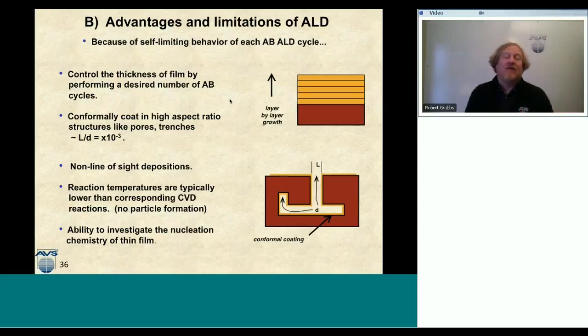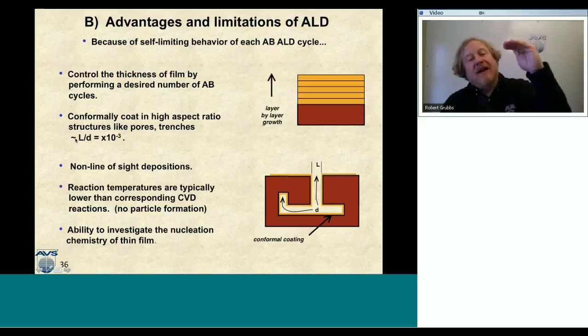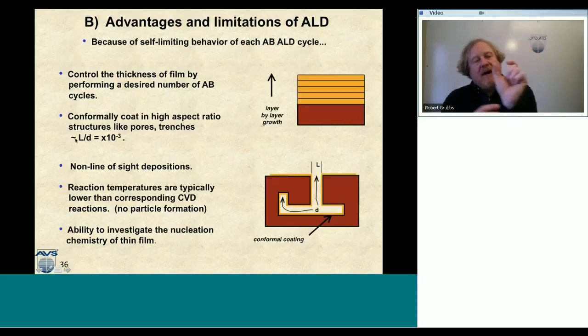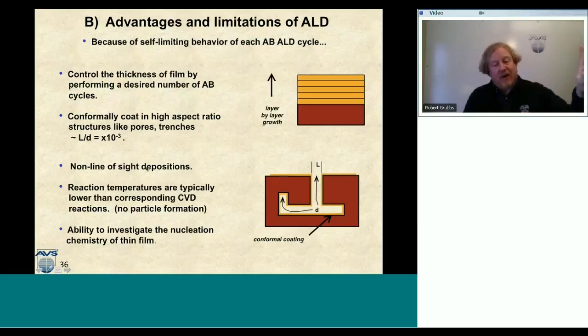So it's very exciting. And if you look at the aspect ratios, that's the length of the trench divided by the diameter of the top, you can get things, that should be a +3, sorry about that, that you can coat aspect ratios of 10 to the 3, which is a remarkable achievement for a certain chemistry. It opens up all sorts of application space. So these can be pores or trenches or tortuous paths, even non-line of sight deposition. You can get your chemistry in up under a shelf, and you'll get the same thickness there as you will